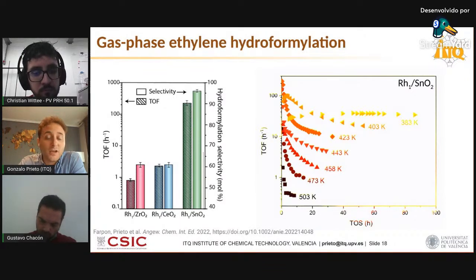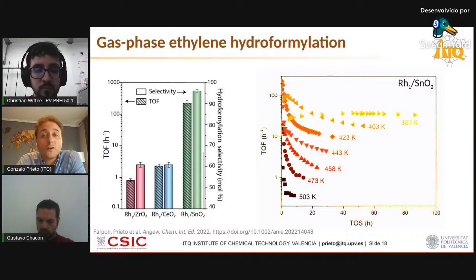Yes, why not? It would fit the definition, which is more generalized for single atom catalysis. As long as there is no rhodium atom within the first, and of course even the second coordination shell of another rhodium atom. If there is, then the answer would be no. What you have is an oxo metal cluster or a metallic cluster. Okay.